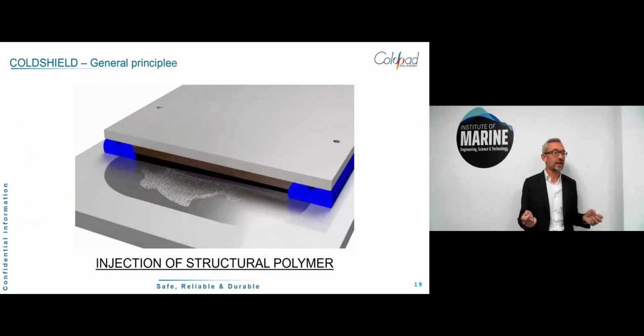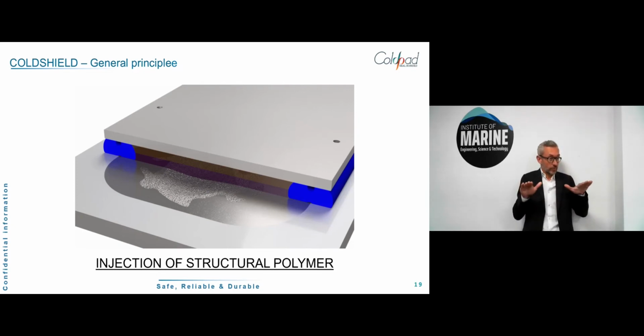Once we've reached the desired atmospheric parameters, then we inject under vacuum the structural polymer, which is epoxy resin. And what is interesting here is that we take advantage of the vacuum to have the seal compressed and to have the polymerization, the hardening of the resin, while it's under vacuum. So the seal, which is compressed during the installation, will remain compressed for the whole service life. The typical linear force is something like 1.5 ton per linear meter, so it's quite strong. And actually, the top plate is deforming due to the pressure difference.